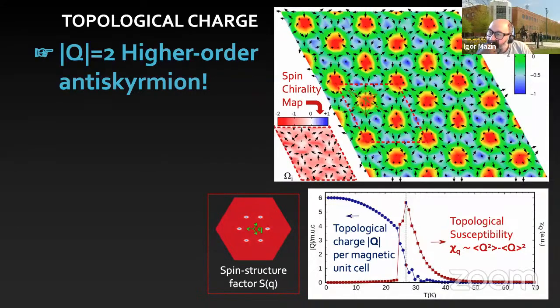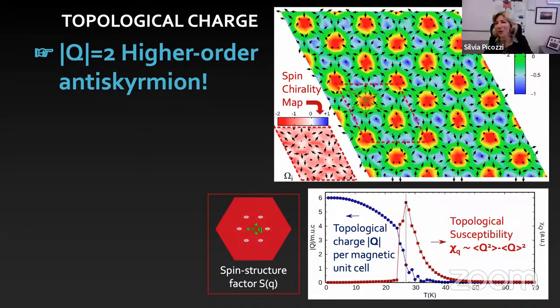Okay, I don't think you can get an anti-skyrmion if you don't have... of course, if you kill spin orbit coupling, the anisotropic exchange is zero, so you're basically left with the Heisenberg. That's right. So basically I'm aiming at establishing whether this skyrmion is really a relativistic effect, or maybe, I agree that it's less likely, but it's not impossible, a pure frustration effect. Right, okay. As I said, for example, I think we tried at some point, I thought, okay, well, anisotropic exchange is really instrumental. So I think we killed it, and then we didn't get the anti-skyrmion. So this is why I say that the system needs to be frustrated in the background. So I need this J3 over J1 as the main ingredient, and then on top of this, if I have this non-coplanarity, then I get the anti-skyrmion. This is what I would say I learned.